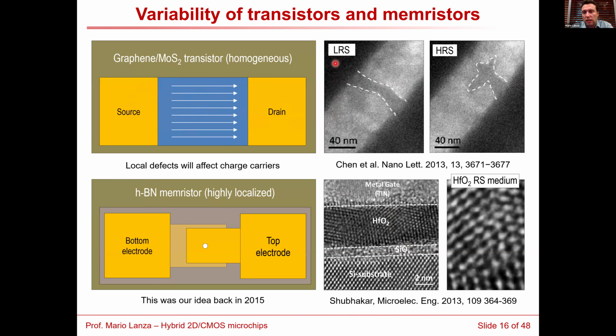The memristor consists of a top electrode and a bottom electrode that are separated by an insulating material. And when we apply an electrical field between both of them, we can trigger a dielectric breakdown, similar to lightning in a storm between the clouds and the ground. And this triggers the low resistive state. And when we reverse the polarity of this electrical field, we can partially disrupt this filament and trigger a high resistive state. You can see that the breakdown only takes place in one specific point of the sample, okay? This is a local phenomenon that in fact is called the weakest link phenomenon. It only takes place at the electrically weakest location of the sample.